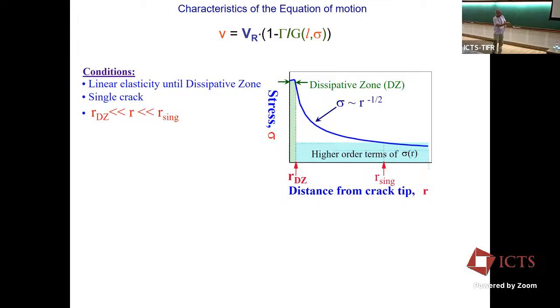Now there are many other contributions to the stress field. This is just the dominant one as we go close. And usually in fracture, because this is the easiest one to deal with, we talk about just the singular fields, and we ignore the higher order terms, which is fine. We've assumed an infinitely large medium, and when we do that, this equation of motion actually is very strange, because